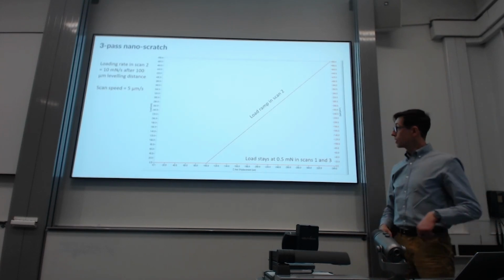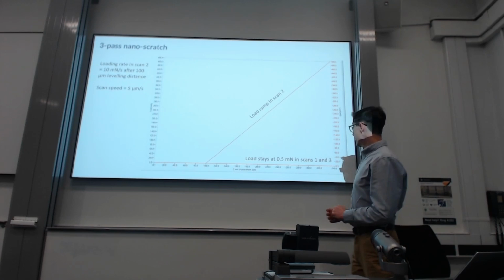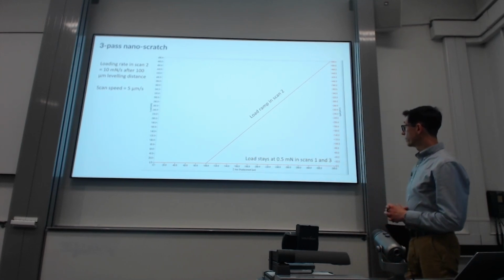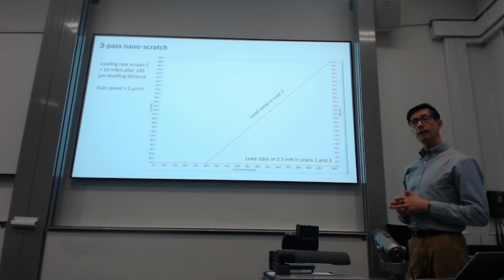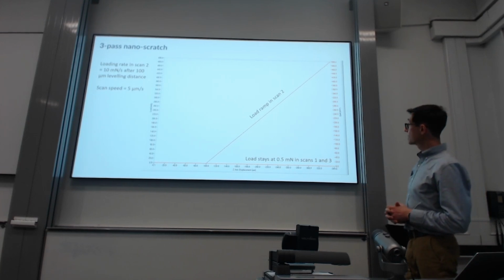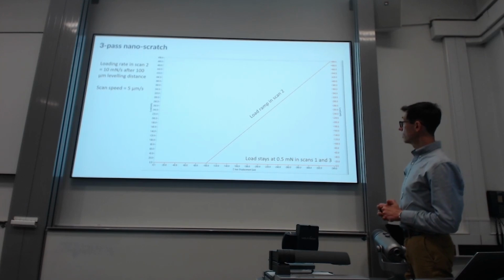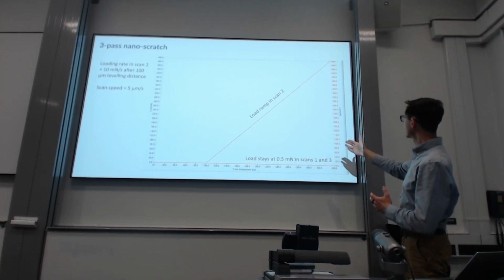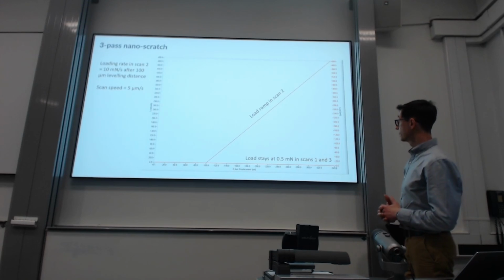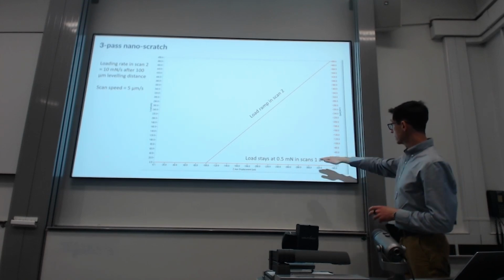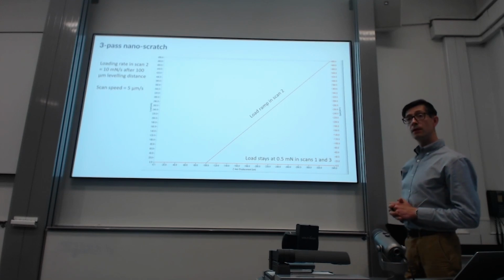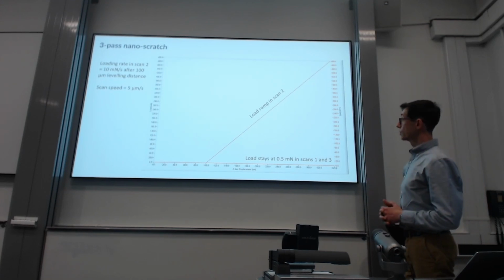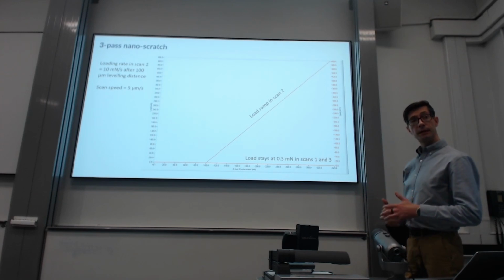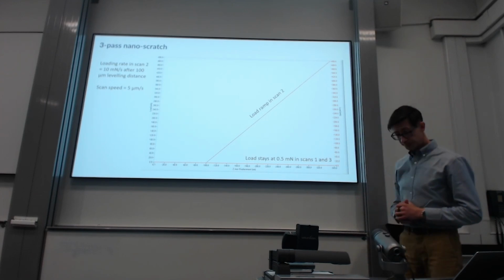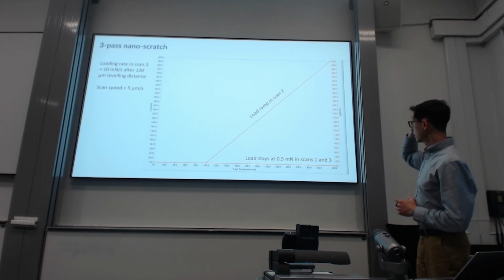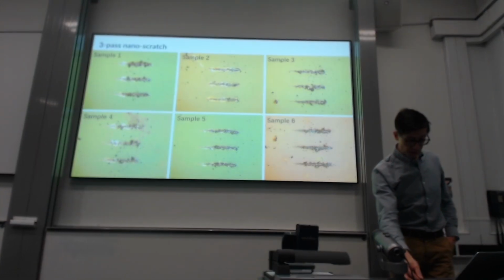So, the 3-pass nano scratch test. Just as a reminder, for your first pass, you go with a minimal load of 0.5 millinewton just to get the surface profile from the scan. Then in the second scan, you ramp up your load, and depending on the conditions, you can set the experiment to a depth, to a load that you want to achieve. And then again, in the third scan, you apply minimal load so that you can get a surface profile after that ramping load event. And you can also extract load and correlate that to friction.